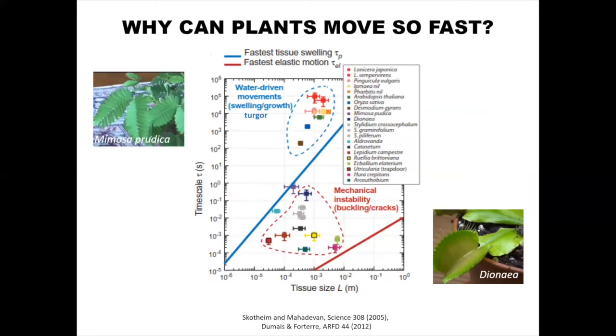And there was some work done by biologists, but also mechanical engineers that looked into what are the mechanisms behind these fast movements of plants. And what they basically found is that there are two major driving forces behind them. What you see up here is water-driven movements, swelling and growth, due to the cell pressure of the water into the cell, the sugar, like Barbara mentioned before. And down here, you can see the other big driving force is mechanical instabilities, so buckling and cracks. This is basically used for expelling seeds quite often.